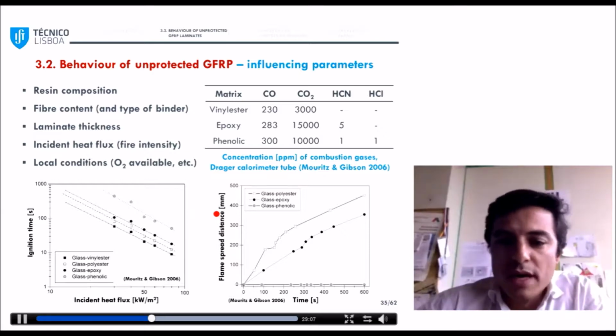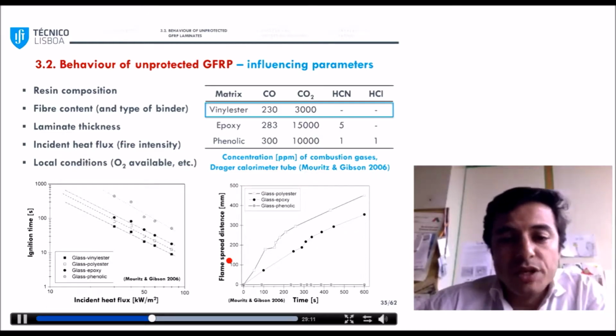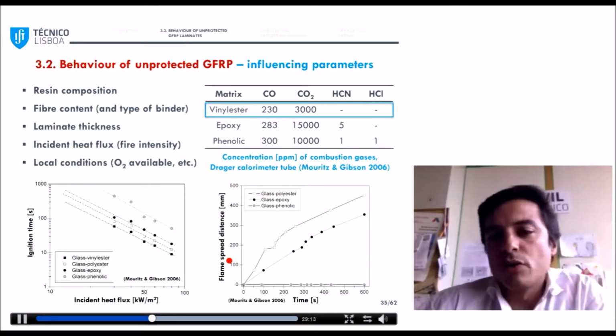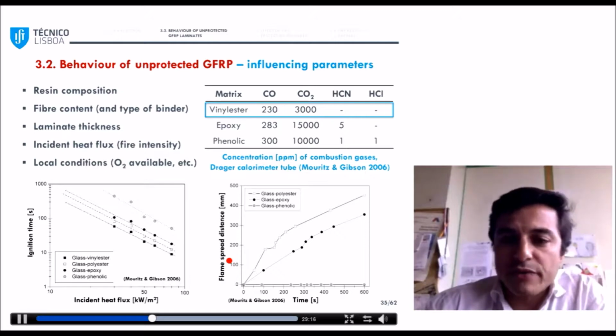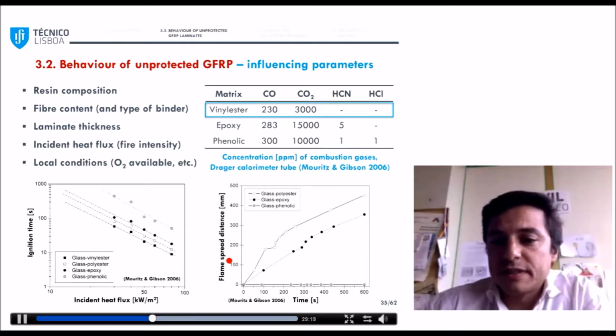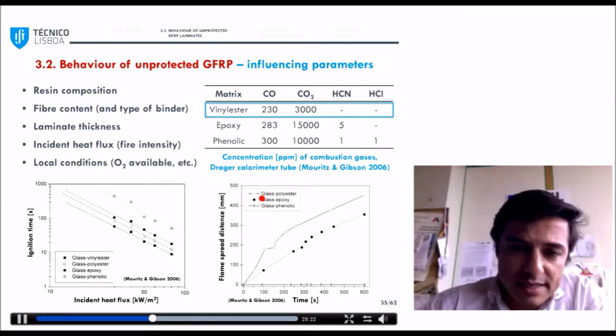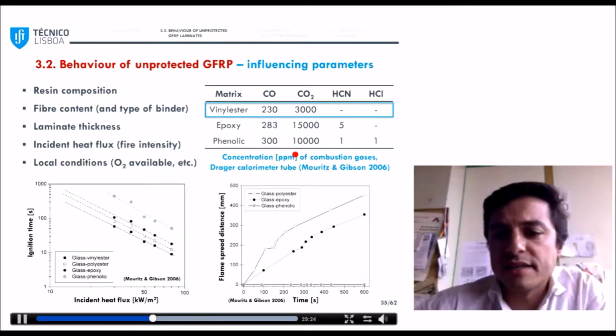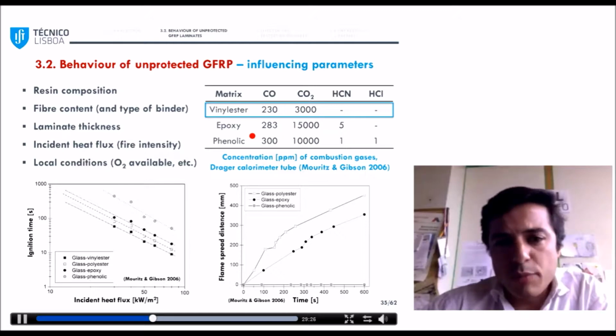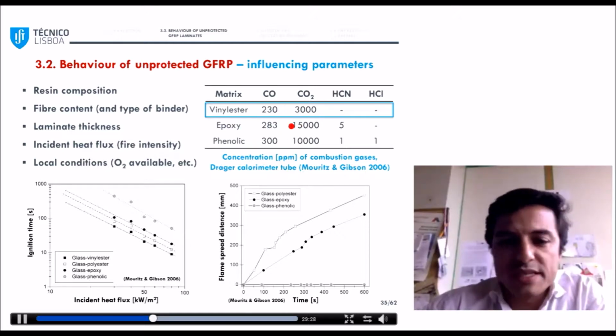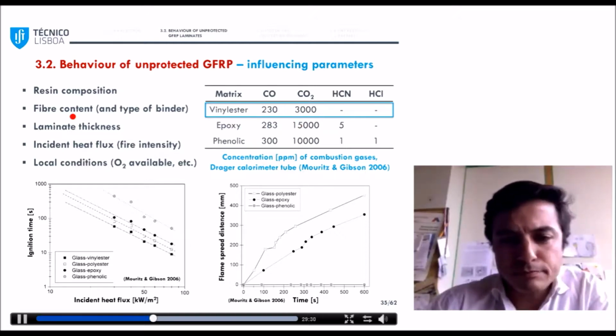In terms of toxic gases, in this table here above, you can see that the different resins release high quantities of CO and CO2, and for vinyl ester, which together with polyester is among the most used resins in FRP profiles, you see that there are no traces of highly toxic gases, as reported by these colleagues, Mouritz and Gibson, while for epoxy and phenolic, you see some traces of these two gases.